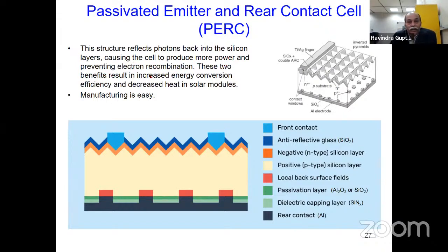These two benefits result in increased energy conversion efficiency and decreased heat in solar modules. So if we have recombination, as you saw, we have phonons because of the heat, which is not good at all. So if we reduce the recombination, naturally we have low heat generation. So PERC helps. Here you can see, we have passivation. This reduces the recombination with the minority charge carriers, the minority charge carriers here as well as the minority charge carriers in the P region.